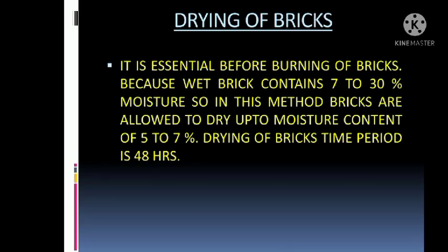Next is drying of bricks. It is essential before burning of bricks because wet bricks contain 7 to 30% moisture. So in this method, bricks are allowed to dry up to a moisture content of 5 to 7%. The time period for drying is 48 hours.